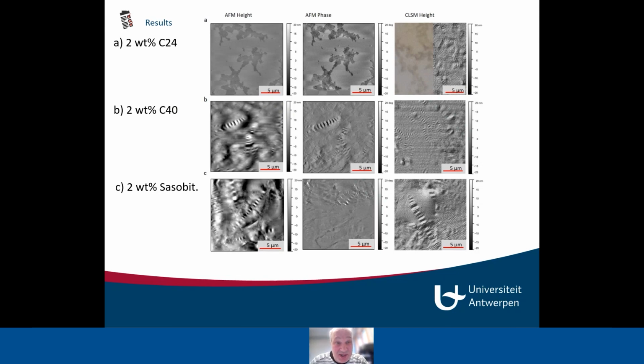So the next step was we started to use this wax-free bitumen, and we added alkanes with different chain lengths to it. We started with 2 weight percent of C24, and then we saw that we couldn't see any bees. We can see some phases. It seems that the wax is not really dissolving, and we have these different areas. And we could see this in AFM, and we could also see this in the confocal.